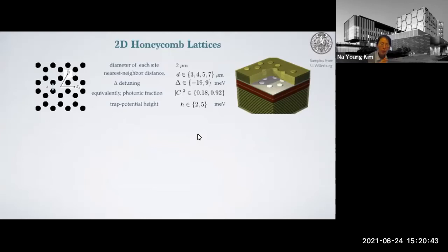So in this case, we are designing these lattices. The way we do it is a honeycomb, which is very similar to graphene. At each site, we set this diameter, and we are using an etching technique. There are several parameters we change. The first parameter is D. D means the site-to-site distance, the nearest neighbor, center-to-center distance, and we vary it from 3 to 7 micron.